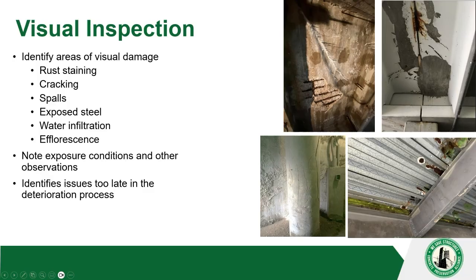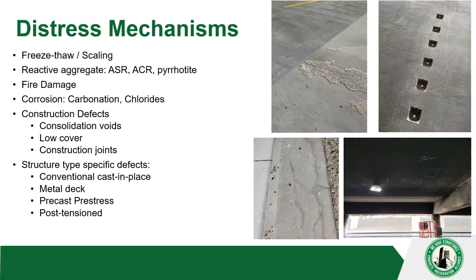And then here, this is your metal pan decks. When you see the corrosion on the bottom side, there's a lot of corrosion on the top side of these metal pans. So here are the distress mechanisms that we're going to be looking for. We're looking at freeze-thaw and scaling. Anything that cracks the concrete is going to let chlorides in, right? So freeze-thaw and scaling is what we see here.